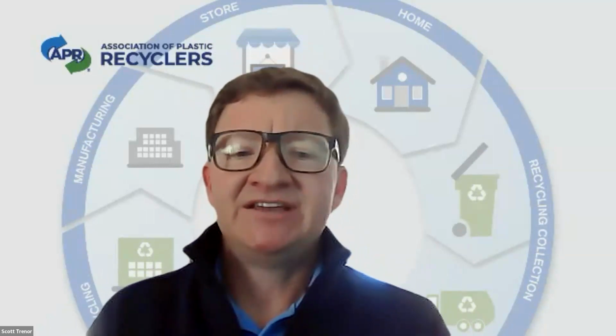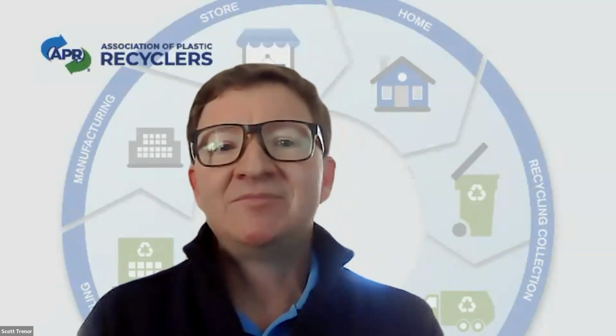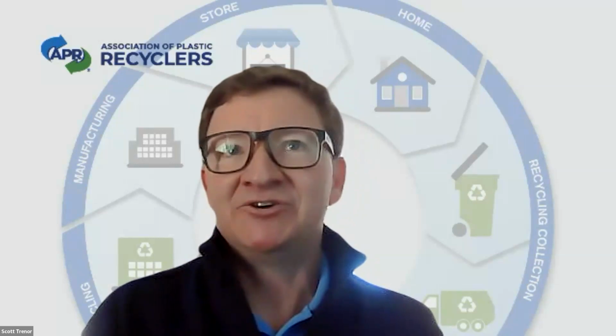So as you talk about not just PHAs, PHBs, but that family of materials, right? I think Closed Loop Partners did a study that said that if people see compostability, they are more likely to think that they can litter it and it'll just go away in the environment. Whereas that might be accurate in terms of some of the PHAs and PHBs available on the market, you're still losing the value of that material in the stream. So even Total Corbion and NatureWorks have moved away a little bit from compostability, and they want you to mechanically recycle that material because there's embedded energy and greenhouse gases in the production of PHAs, PHBs, PLAs, PBATs, any of those compostable materials, right?